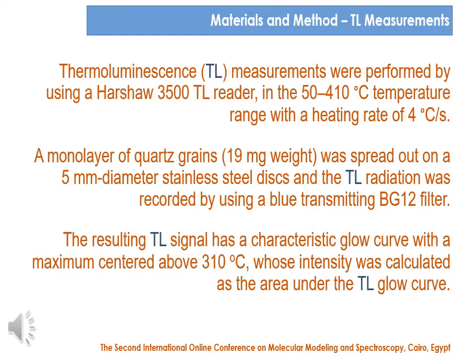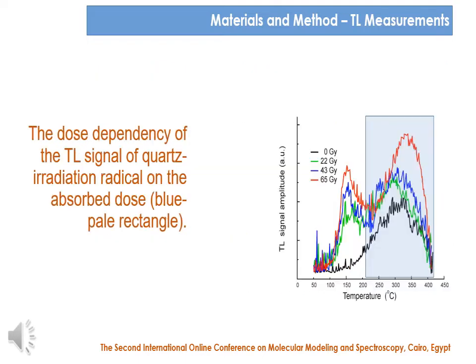At their turn, thermoluminescence measurements were performed in the domain of 50 to 410 degrees centigrade with a heating rate of about 4 degrees Celsius per second. A monolayer of quartz grains was spread on a 5 mm diameter stainless steel, and thermoluminescence radiation was recorded by using a blue transmitting filter. Resulting TL signals has a characteristic glow curve with a maximum centered about 310 degrees, as illustrated in the next slide. Here you can see the thermoluminescence signal whose intensity increases with the absorbed dose.